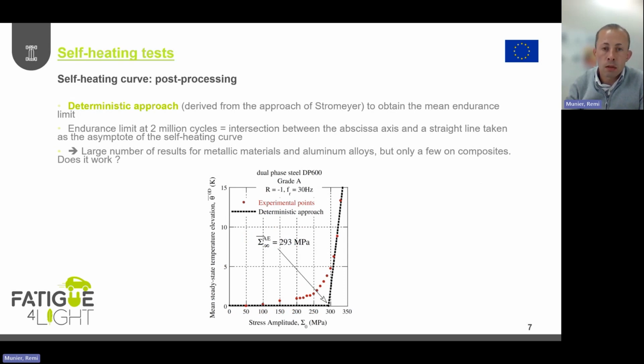First, as Stromeyer used more than one century ago, the idea is to use some kind of deterministic approach to determine an estimation of the mean endurance limit at 2 million cycles. Here we consider that the intersection between the axis and a straight line, which is taken as an asymptotic behavior of the self-heating curve, is the mean